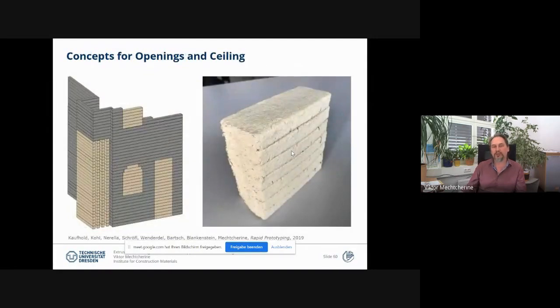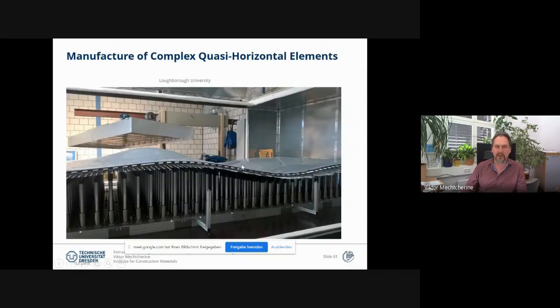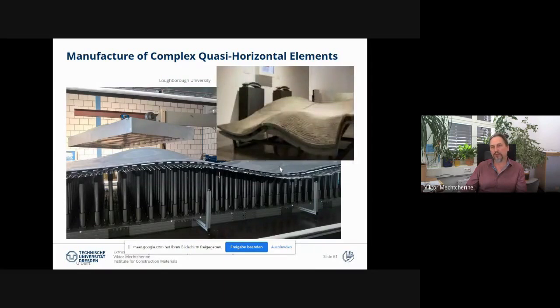What we also suggested is to use other 3D printed material, which is kind of disposable. In this case, we use a mix of wood chips and starch to produce a material which serves as a support material, but that can be removed easily and recycled and used again for further applications. Otherwise, if you have more, let us say, fancy geometry, you can also use this kind of curved mold and deposit material on this mold, again using 3D printing, as this example from Loughborough shows.